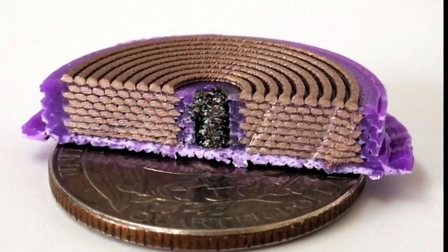Because their machine could print with a more effective soft magnetic material, the solenoids achieved higher performance than other 3D printed devices. The printing method enabled them to build a three-dimensional device comprising 8 layers with coils of conductive and insulating material stacked around the core like a spiral staircase. Multiple layers increase the number of coils in the solenoid, which improves the amplification of the magnetic field.